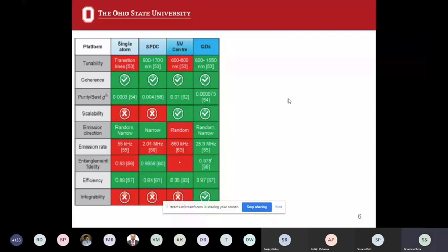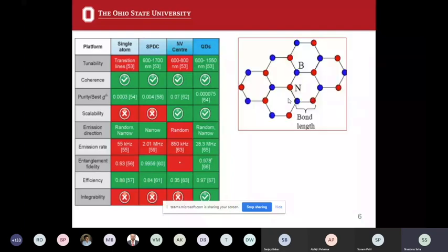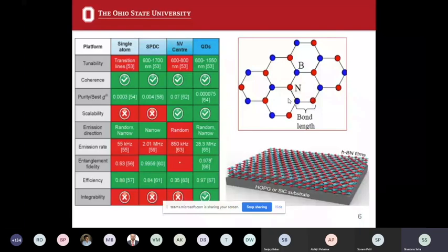So we are currently focusing on hexagonal boron nitride. You can see this hexagonal structure where boron and nitrogen are bonded with each other. And this is the material that we have deposited. So you can see hBN thin films were deposited on HOPG, highly oriented pyrolytic graphite substrate, or silicon carbide substrates. We are also thinking about depositing our hBN thin films on sapphire substrates.